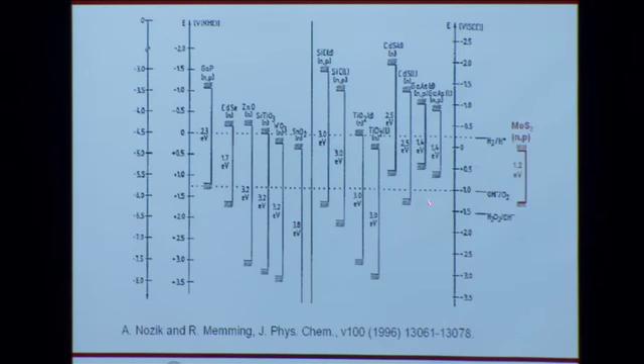These are the valence band and conduction bands of a number of garden variety semiconductors that you'd likely come across. We have hydrogen evolution and oxygen potentials shown on this diagram, and the first thing I'd like to point out is that very few of these semiconductors actually straddle the redox potentials of hydrogen and oxygen. That's a necessary requirement, as I was describing earlier. Those that do typically are very wide bandgap semiconductors, like silicon carbide with 3 electron volts. That means it only absorbs UV light. That's not going to cut it in terms of efficiency. The smaller bandgap materials, like say gallium arsenide, have band edges located too high. That's true for silicon as well.